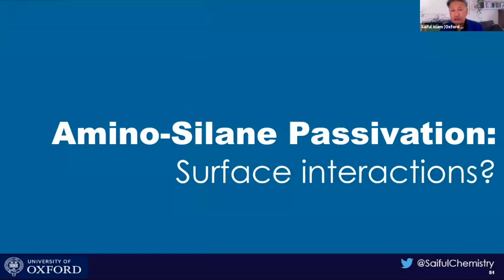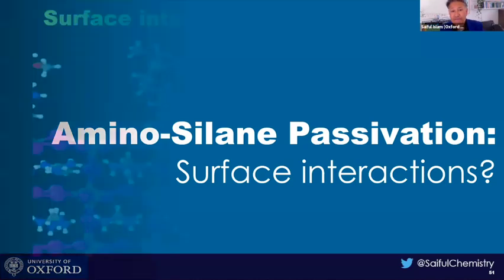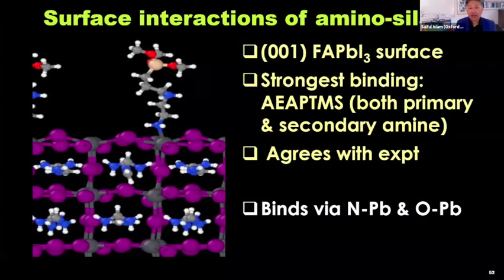So what's the surface passivation mechanism? It works, but why does it work? What's happening? And what we found is that it does indeed interact with the surface. What I'm showing you on the left is a slice through the surface. The purples are the iodide. The dark grey is the lead ions. And you can see the formamidinium molecules in the bulk. Above that surface, I'm showing you one particular aminosilane, in this case the AEA-PTMS, the starting configuration.